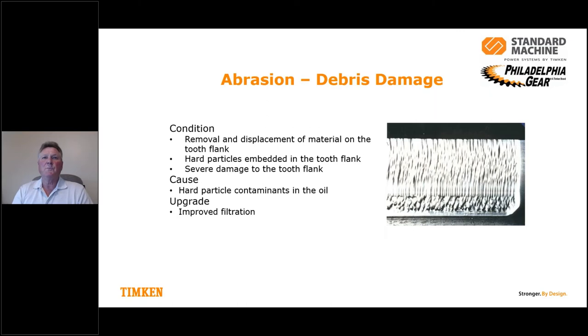Abrasion, so debris damage. The condition is, you're removing a lot of material on the tooth flank. We refer to the tooth flank basically as the part of the tooth that rolls in and out of contact with the mating gear. So there's hard particles that are embedding in the tooth. It's very easy to see that something is squeezing in there, and it's debris. Something's getting trapped between the two gear surfaces, and it's causing a lot of damage to the gear tooth.